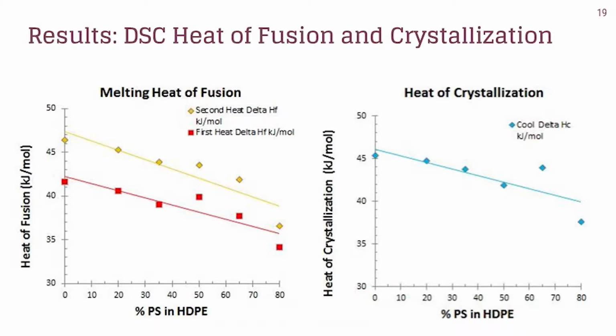By taking the area under each curve, we were able to get the melting heat of fusion and heat of crystallization, which showed a steady decrease as polystyrene content increased.